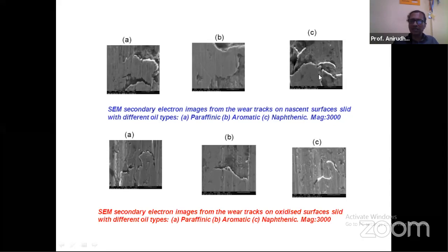So your SEM images are indicative of the amount of surface damage, and that is getting correlated with your resistance to motion, because there is very large scale deformation and plasticity happening in the cases shown above on the top figures as compared to this. So you can exploit these features from your SEM to substantiate the results that you have found from your tribological experiments using a pin-on disc, a sliding experiment, a fast oscillating machine and things like that, or even your 4-ball tester.